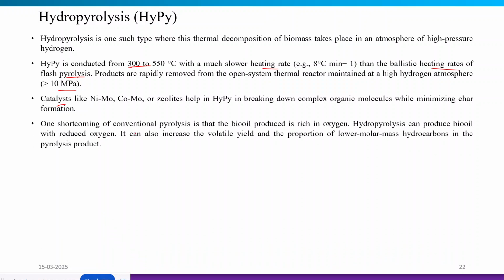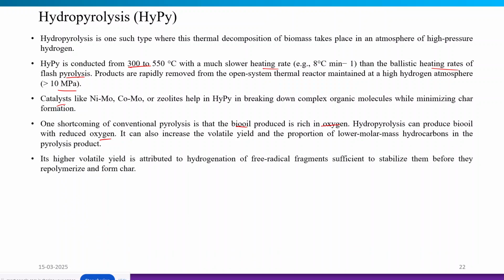So, one shortcoming of the conventional pyrolysis is that the bio-oil produced is rich in oxygen content, that we were discussing in the last slides. But in case of the hydropyrolysis, it produces the bio-oil with reduced oxygen. It can also increase the volatile yield and the proportion of the lower molar mass hydrocarbons in the pyrolysis product. So its higher volatile yield is attributed to the hydrogenation of the free radical fragments sufficient to stabilize them before they repolymerize and form the char.